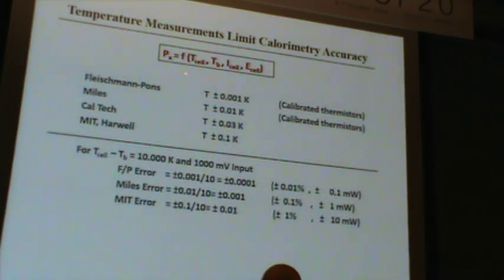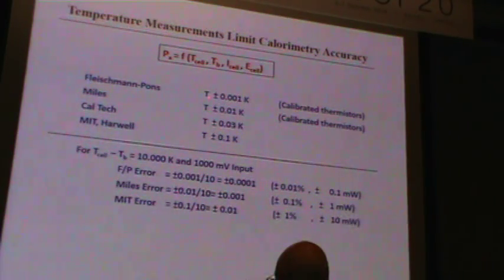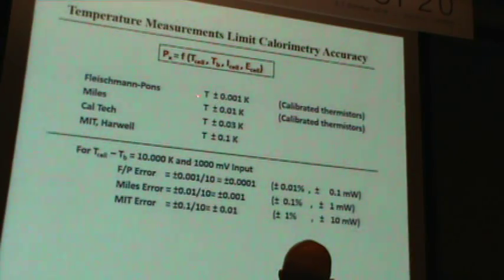In doing calorimetry, you measure four things: the temperature of the cell, the temperature of the bath, the current of the cell, and the voltage of the cell. The least accurate measurement is the temperature, and your calorimetry is often limited by that temperature error. They calibrated and reported their values to 0.001 degrees. I only go to 0.01, Caltech 0.03, and MIT and Harwell 0.1, and so, for example, MIT can do no better than plus or minus 10 milliwatts.